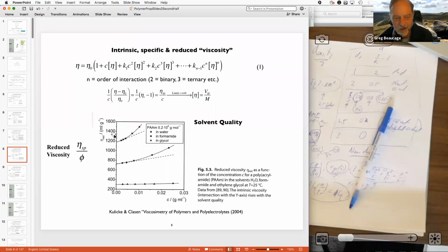So you don't know if it's a more expanded coil. If it was the same conditions, you'd say it's a more expanded coil. But basically, because the conditions change, which is the thing you're trying to see if it expands in, then you can't tell, because the draining would change. Right, so this is a tricky number to mess around with. Anytime you take kinetics and try to get structure or thermodynamics from it, you have to be really careful. It's almost not possible to do it, right? Morphology from rheology is theology, is the old expression. So you have to be pretty careful what you're doing.